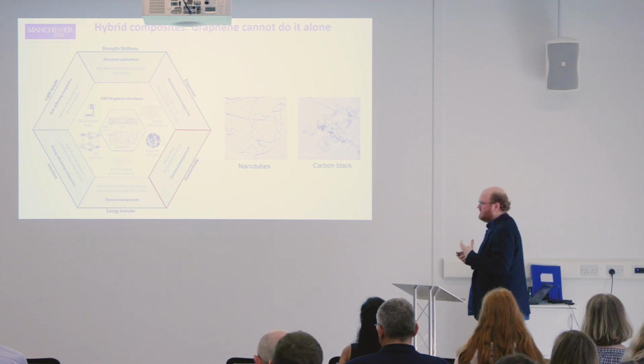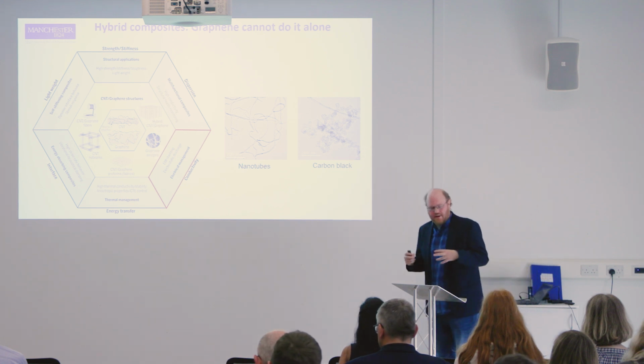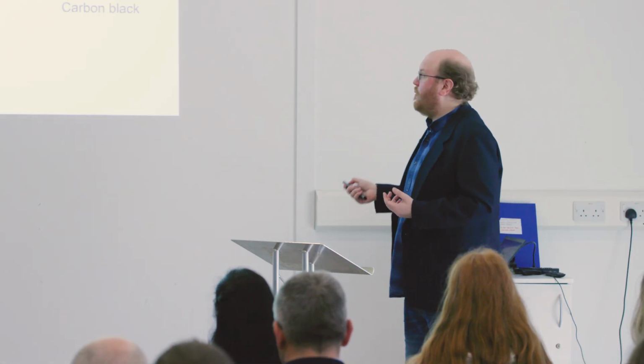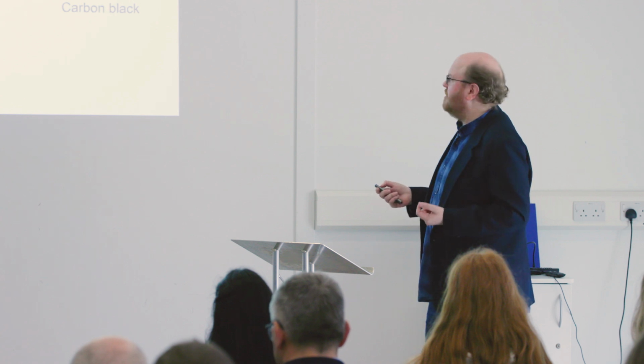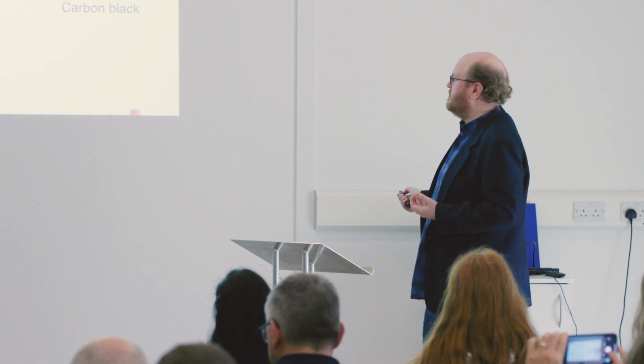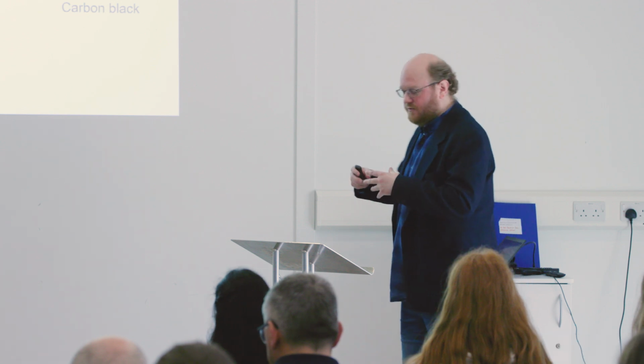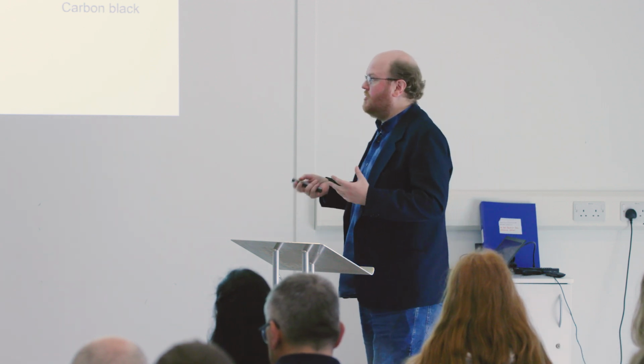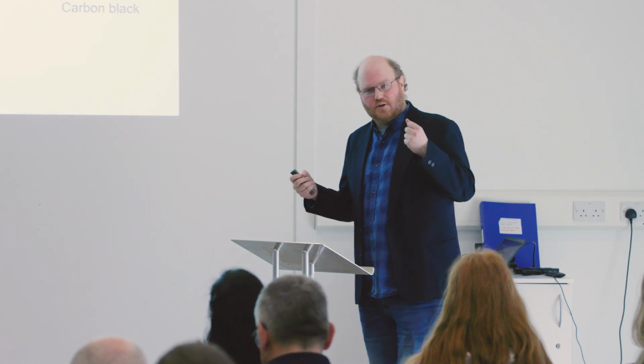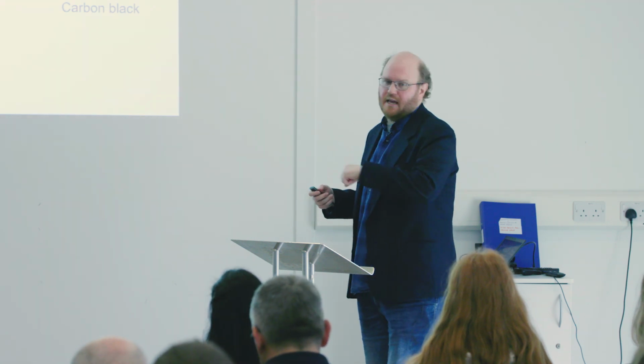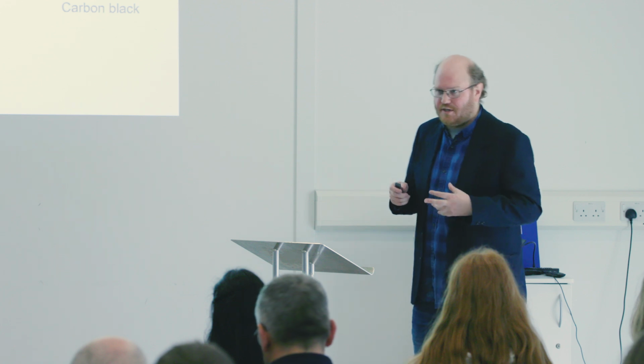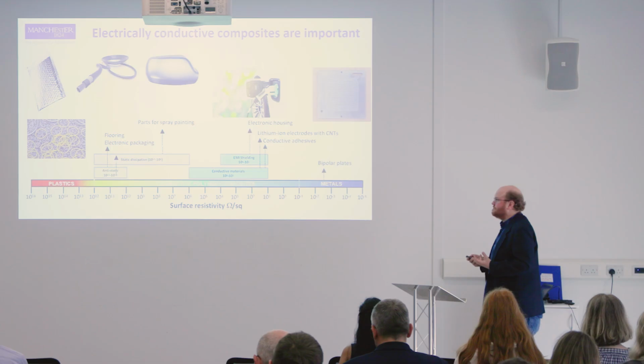And what we've found is that to achieve these multifunctional benefits, it's about that synergy. It's about combining multiple nanomaterials together and not just any one. So when we look at older nanomaterials, we've got 1D materials like carbon nanotubes, or 0D materials like carbon black. These are traditional conductive additives. So when looking at electrical conductivity, we thought, let's look at the combination of graphene, nanotubes and carbon black. Let's see how they interact with each other, and if we can get any synergy from them.